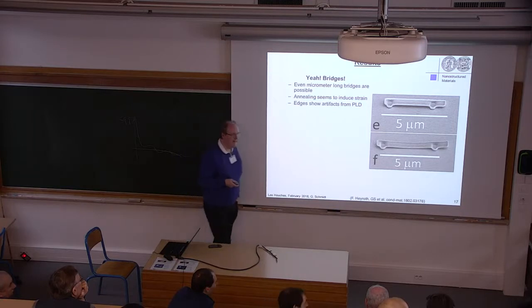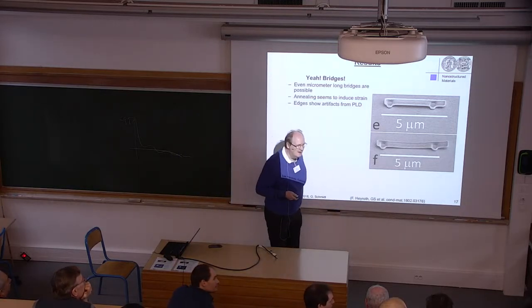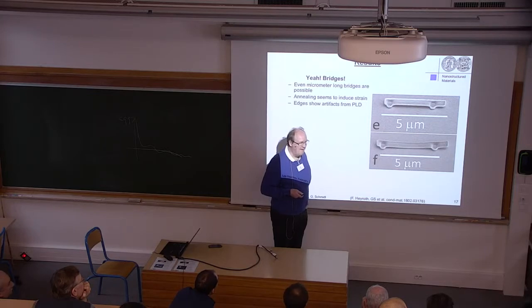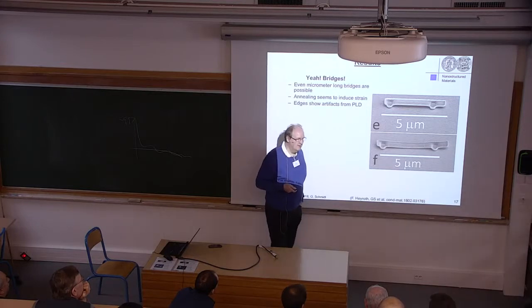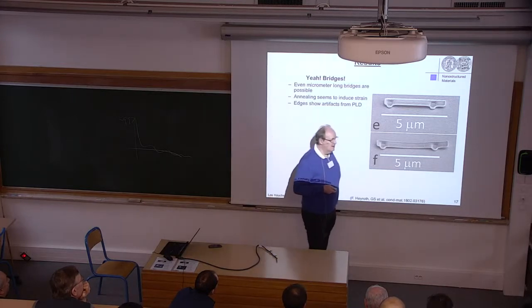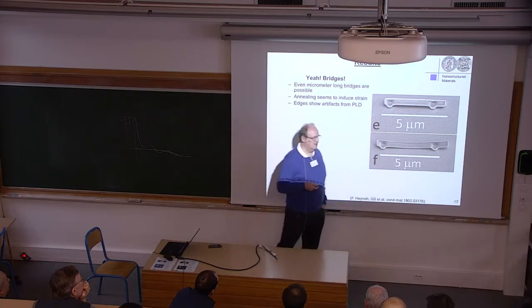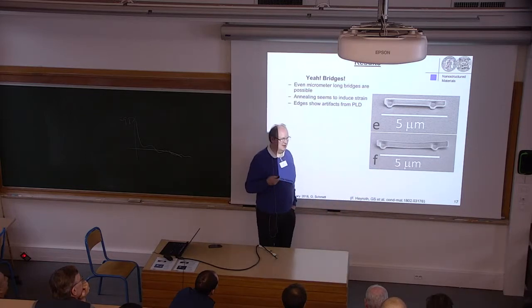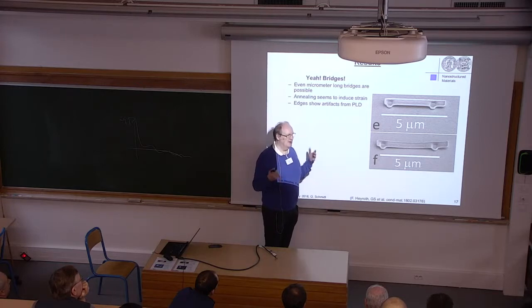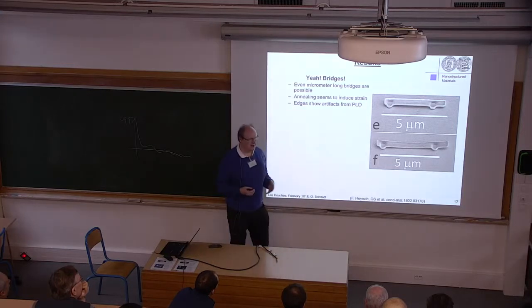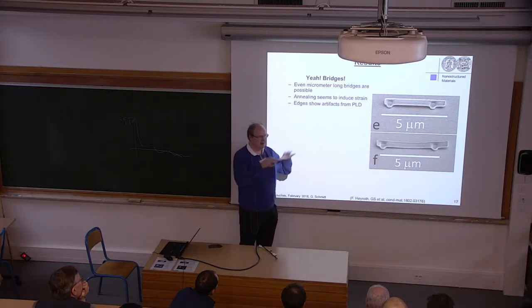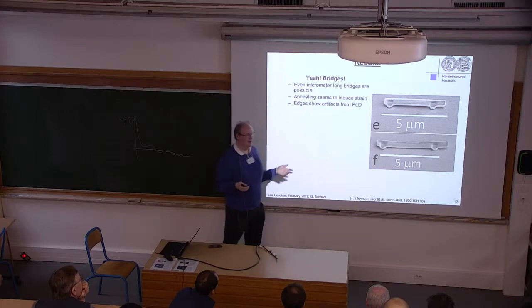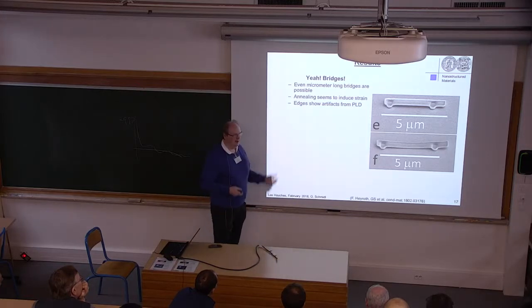Are you going to say more about this special YIG target? Like the morphology of that unannealed film, the lumps and stuff, is that from large chunks coming off from the PLD? So the target that we're using has been mixed by Stefan Ebbinghaus, and he's basically just been using all the stuff that you have to mix together to get YIG in the end. The surprising thing was that first we got a recipe from Munich, and he did some annealing and tried to get it as crystalline as possible. But in the end, it turned out that just having the mixture compressed is fine.